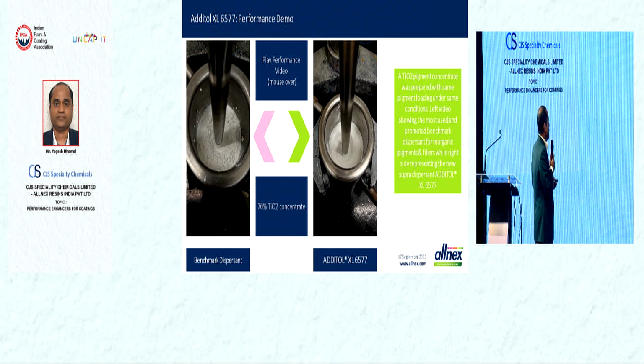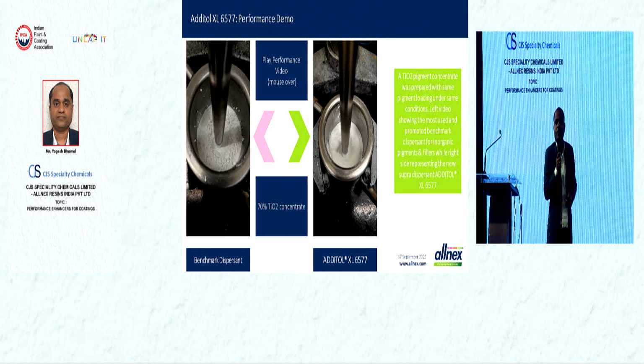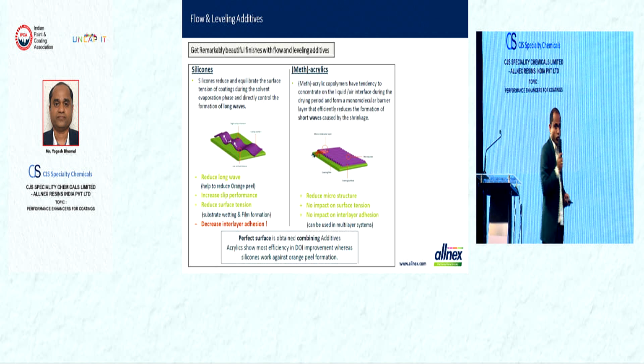The 70% titanium dioxide has been dispersed under similar conditions, and you can see the right side video and left side video. Here in the left side video, the normal conventional type of dispersant has been used, and on the right side, our XL6577 has been used. So you can see the clear difference in the performance of ADDITOL XL6577 to achieve the proper mill-base viscosity reduction. So that was our hero product under the pigment wetting and dispersing category.